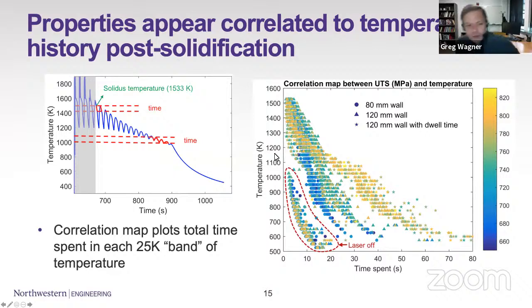And again, the trends are not perfect, but there are some clear trends here where the larger the amount of time spent in this kind of middle temperature range, around maybe 700 or 800 to 1000 degrees K, the higher the ultimate tensile strength. And you can see some of this through the solidification region, but things are much more pronounced. This separation is a lot more pronounced during this kind of middle temperature range. Okay, so there seems to be something going on there, even if we don't have an obvious way of quantifying it.